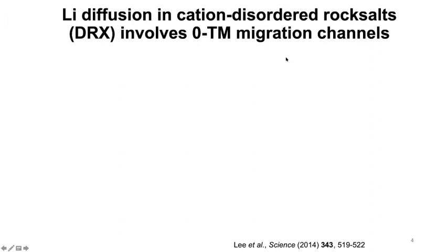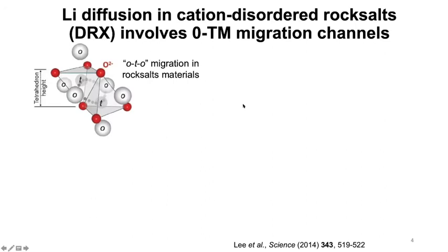Actually, for quite a long time, people believed that fast lithium-ion diffusion in DRX material is not possible because of cation disordering. However, later researchers found that this is not correct. In both layered rocksalt and disordered rocksalt, lithium migration happens through this o-t-o mechanism, which means the lithium migrates from one octahedral site to the neighboring octahedral site through an intermediate tetrahedral site. It happens via different tetrahedral coordination environments.